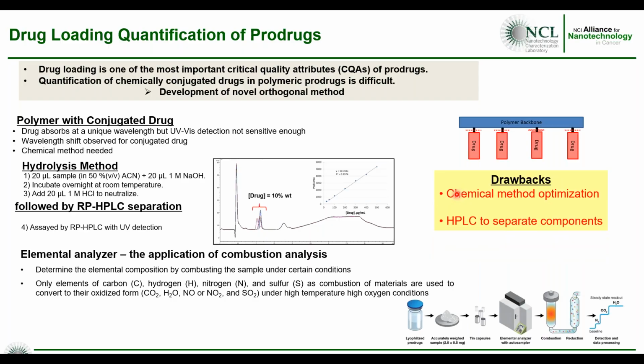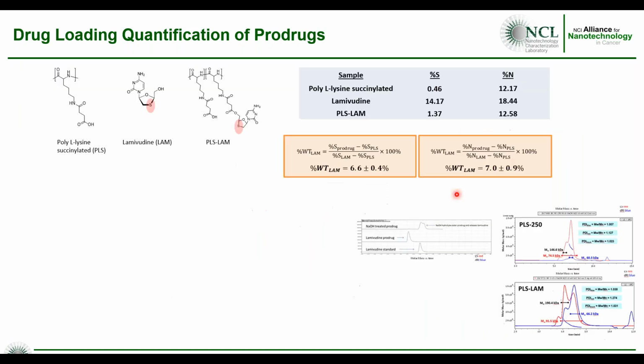So we came up with a new method whereby we're using a very old technique. It's an elemental analyzer. Essentially, you're combusting the sample and you're looking at the carbon, hydrogen, nitrogen, and sulfur content of your sample. And we tested this on our in-house prodrug. So we have a prodrug with this is the backbone, this is the drug, and here's a prodrug with the conjugated drug to the backbone.